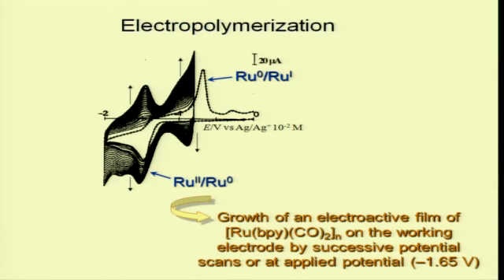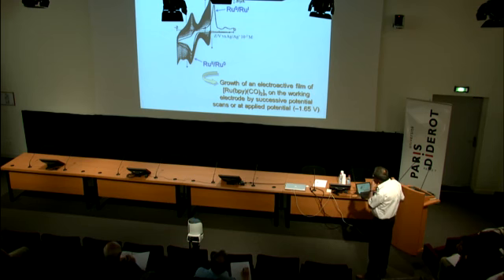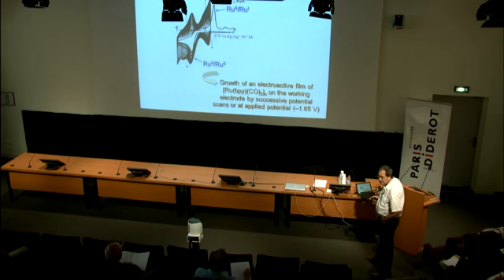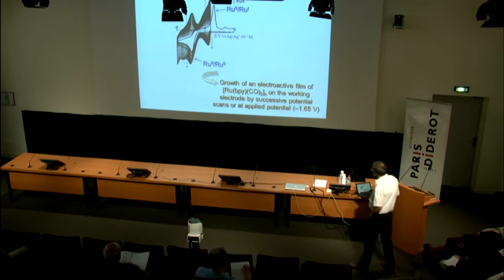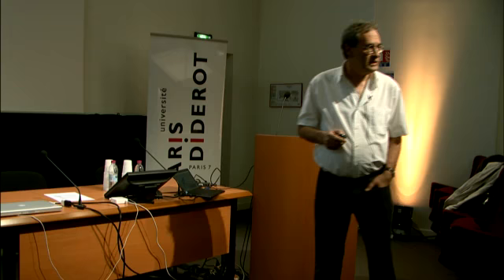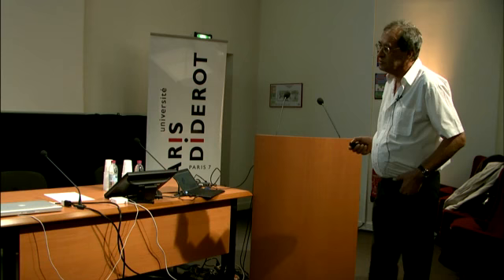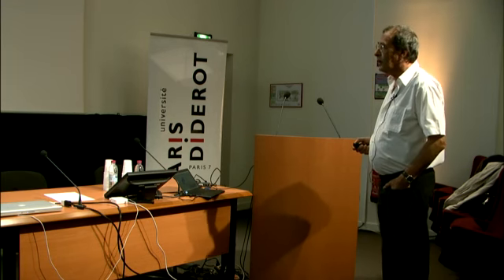So, the process is very efficient. It corresponds to quantitative formation of film. And you can follow the formation of the film by continuously scanning the potential in this area, in the catalytic area. You just have to take care about the potential on the way back. You have to stop returning the potential just before the dissolution of the film. And you can see the growth of 2 signals here, quite reversible, corresponding to the electroactivity of the film itself on the surface of the electrode. But you can also, of course, make the corresponding film simply by applying potential at that potential.